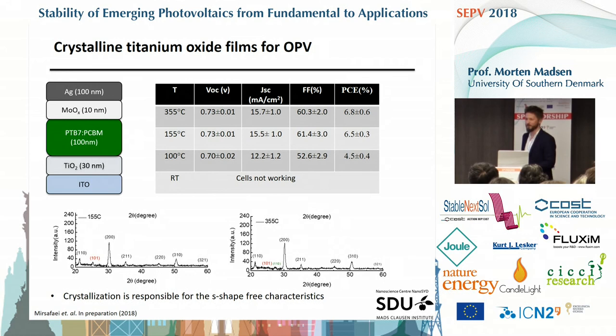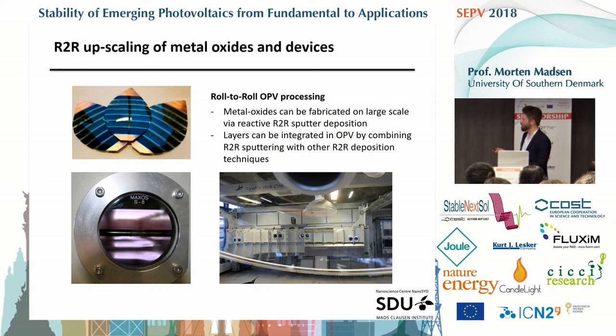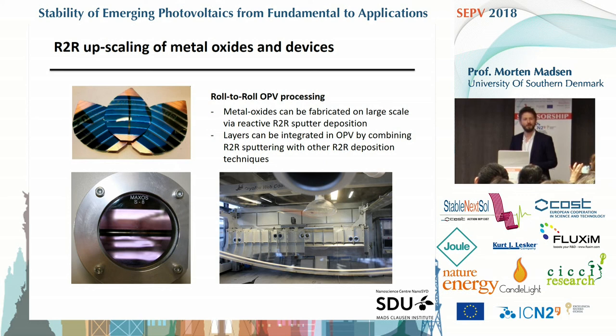The very last slide is more of a motivation slide for future work. Sometimes presenting this, people will say you use high temperatures and sputtering—is that good at all for OPV? We develop roll-to-roll process modules in our lab, and part of what we do is roll-to-roll vacuum deposition. We have a roll-to-roll sputter line, so we do this reactive sputtering also on rolls, and we have started to work on the titanium oxide and would like to extend that to the other oxides. For molybdenum oxide, you would need to lower the temperature more, but there are things you can play with in sputtering processes that can induce crystallization at lower temperatures—you can play with sputter power, pressure, and so on, instead of temperature alone.